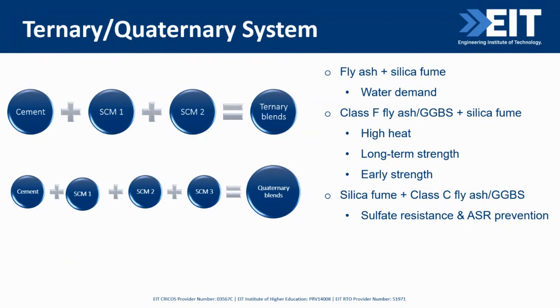So there can be a pronounced synergy in combining different supplementary cementitious materials, either fly ash, slag cement, or silica fume. For example, silica fume can offset the increased water demand of fly ash, and Class F fly ash or GGBS actually compensates for the high heat released from the blended cement with silica fume, and also increases the long-term strength development of silica fume concrete.